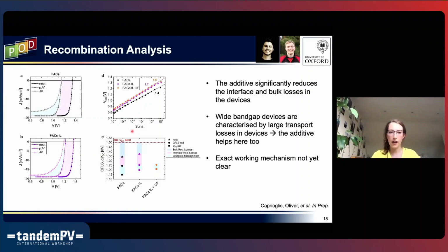So if we look at how our VOC changes in different measurements, this blue box here is going to represent how much bulk recombination loss we have. So that's going to be any of that non-radiative recombination that's happening just within the material itself, this loss between this red line, which is our radiative limit of our VOC, compared to the triangle. And then this pink box represents our interfacial recombination losses. And then anything we lose beyond that, so measuring a real solar cell as opposed to simulating the JV curve, we can assume is some energetic misalignment between our contact layers that we're using.